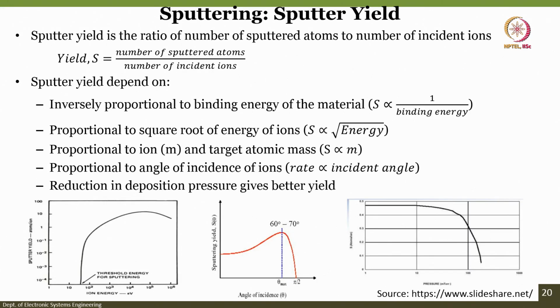So, what is sputtering yield? Sputtering yield, given by S, is the number of sputtered atoms divided by the number of incident ions. That is, how many atoms get dislodged from the source on bombardment by the incident ions. That ratio is called the yield, and it depends on several things. The first is that it is inversely proportional to the binding energy of the material. Second, it is proportional to the square root of the energy of the ions. Third, it is proportional to the ion mass, and the target atom mass, and it is proportional to the angle of incidence, so the rate is proportional to the incident angle. Finally, reduction in deposition pressure gives a better yield.